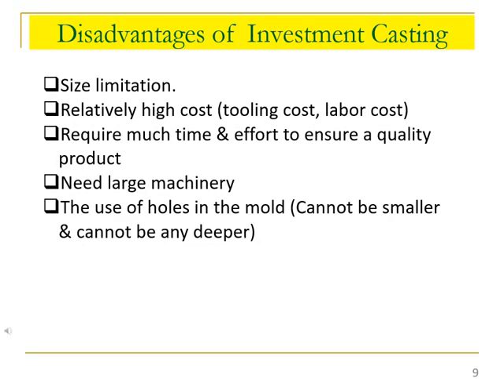Another downside is the initial cost. Although investment casting saves on cost in various ways, preparation work can be labor-intensive compared to other methods; wax patterns and shell molds require much time and effort. Large machinery is required, and when extremely high-volume manufacturing is desired, the associated costs and longer cycle times can make investment casting a less suitable option. Additionally, holes in the mold cannot be smaller than about 1.6 mm and usually cannot be deeper than about 1.5 times the diameter.